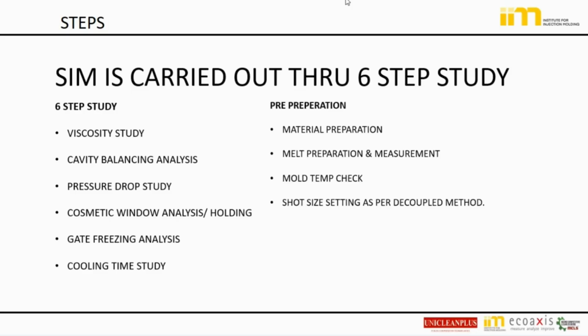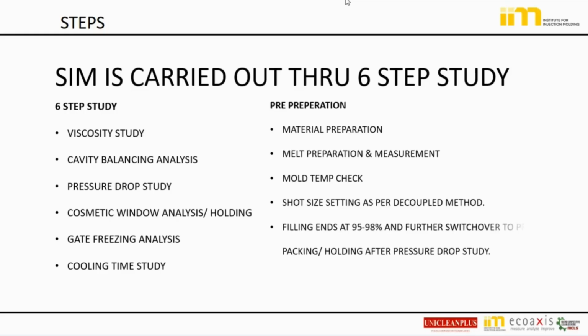At 98% the cavity is almost fully filled, and you can see some seam marks. If you are able to do that, then only will you get consistency. If you are filling only 50% and switching over, there is a lot of variation. So always go to 95 to 98%. I personally use 98%. For some critical parts you sometimes have to go to 95, but 95 to 98% is a good switchover. Then holding adds the remaining 2% volume, the weight of the part.